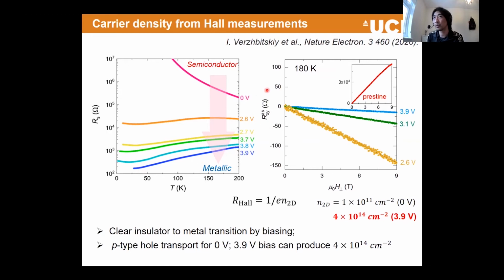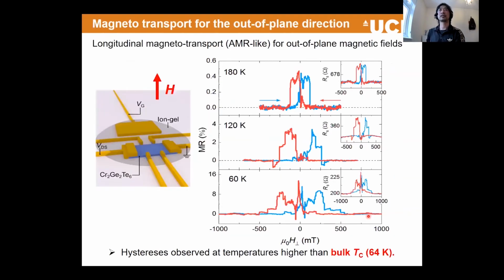And then from this Hall resistance, we can calculate this charge accumulation, which is reasonably high. This is just 10^14 per square centimeter. So that's reasonably large, shall we say. So that's great. And then let's look at the magnetism by the magnet transport.